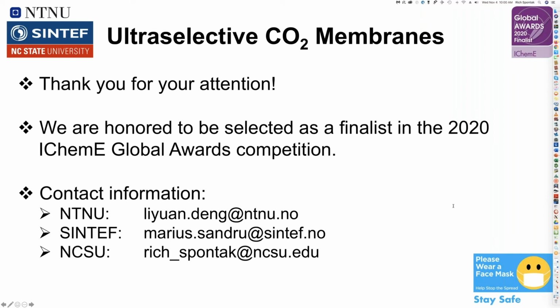It has certainly undergone some intellectual property protection, but the idea is still moving forward, and we were very excited to see these levels of selectivity obtained from two very different starting points, but nonetheless through some type of modification, whether it was to open up the nanostructure of the nanofibrillated cellulose, or to introduce CO2-specific moieties on the surface. We found that both approaches actually got us to where we wanted to be, which was in the high CO2 selectivity threshold.